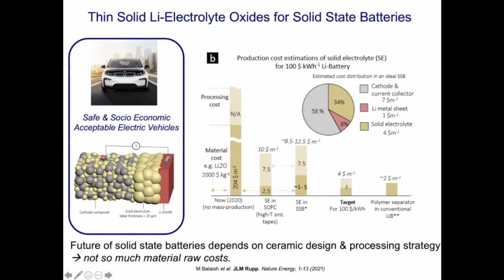So when you do a little bit of the cost analysis, then we quickly realize that to meet the Department of Energy suggestion to have about 350 watt hour per kilogram of storage for a solid state battery system, this would translate to about $100 per kilowatt hour. Now, in terms of ceramics, what it means is the following. So when one does a quick math and one translates what it means in materials and processing, then one has about $30 per kilogram for processing and the materials of a solid state battery, which includes the anode, electrolyte, and cathode.